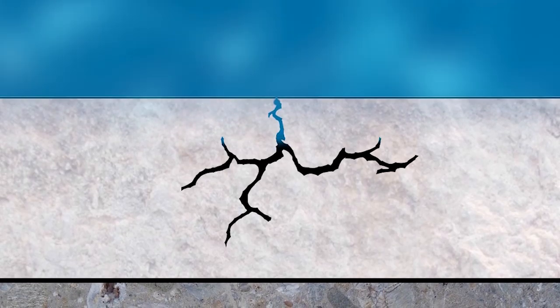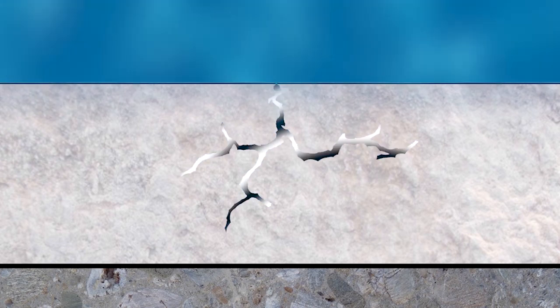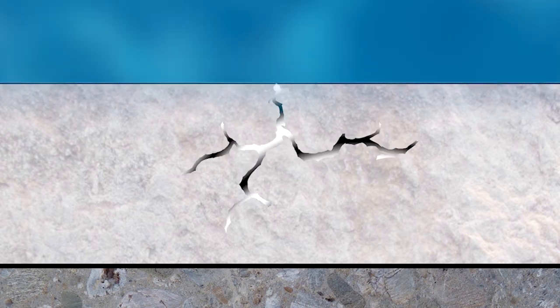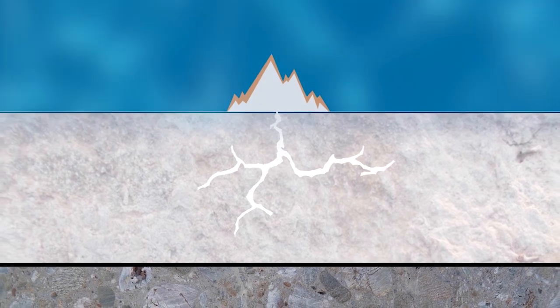The same aggressive water that has removed the cement reaction compounds from the micro cracks can continue to leach soluble cement compounds from the interior of the plaster — known as the sub-boundary layer — through a process called dissolution from a solid to a soluble ion form, and diffusion transport of the soluble ions, then deposit these as a mineral salt on the surface, creating the nodule deposit consisting mainly of calcium carbonate. De-bonded areas can lead to flexural cracks that can also lead to nodule deposits even without aggressive water, as pool water can circulate in and out of these hollow areas and transport soluble salts that then deposit on the surface.